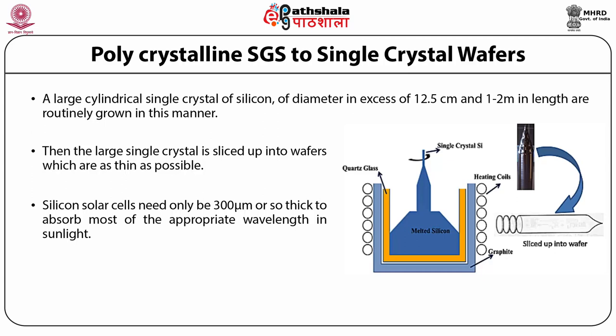However, the cutting of the wafer is quite difficult, which results in the wastage of silicon crystals. Generally, saw blades used to cut the silicon crystal have the same thickness as that of the wafers, and therefore 40 to 50% of the material gets wasted in this process. Moreover, the wafers get damaged while slicing, which needs to be cleaned by acid etching. More often, the sides of these circular wafers are clipped to get either a square or hexagonal shaped cell to have better packing density in a solar cell module.